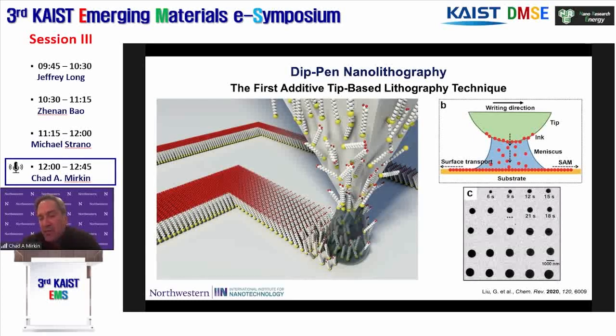And we started with very simple alkanethiols, you can see over on the right. And what you can see is that it acts a lot like a dip pen. You keep it in contact, the molecules continue to diffuse and the features get larger. Short times give you small features, large times give you larger features, all one monolayer high. And this was interesting because it's arguably the first additive tip-based lithography technique. And it allowed you to do it on a scale that was really interesting at the time, the nanoscale.